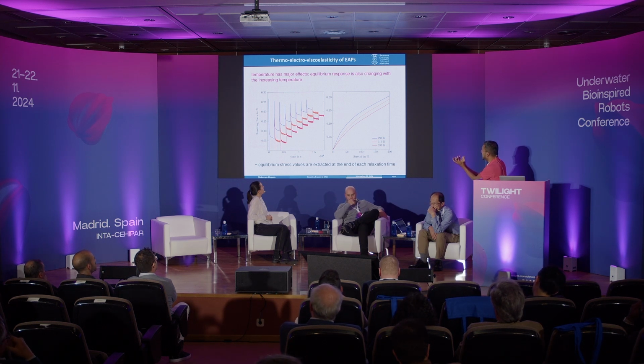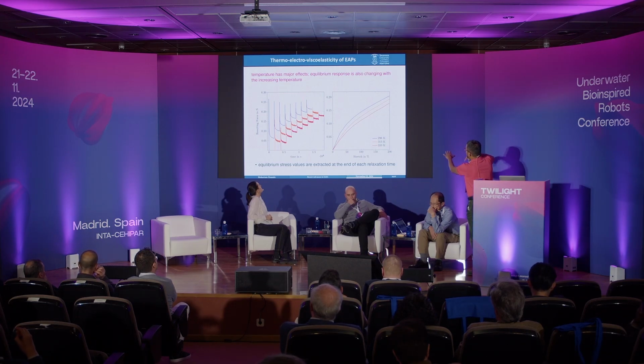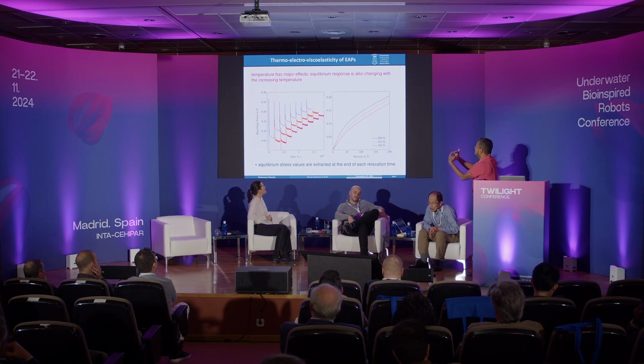And so from there, you can extract the so-called equilibrium stress, and then you can plot. Then you can clearly see that the temperature has a significant influence on your viscous response as well as your hyperelastic response or equilibrium response, both. And then in the same chamber, we apply the electric field.